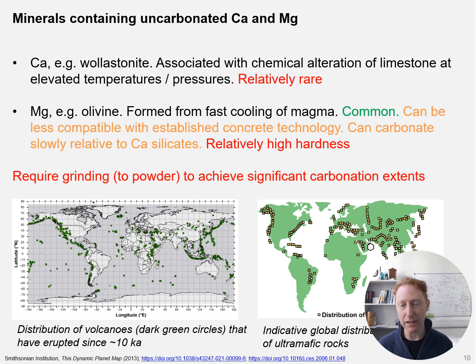So the good thing about magnesium silicate minerals is that they are relatively common. Wollastonite, on the other hand, is much rarer, and so in general has a more limited potential as a feedstock for CO₂ mineralization. Regarding the more available magnesium silicate rocks, magnesium is less compatible with established concrete technology. For example, Portland cement requires limited magnesium content, so it can be used in limited, but still quite a few, applications. Another issue is that magnesium silicate minerals have relatively high hardness, and this is a problem because they need to be ground into a powder or a small particle size to carbonate them significantly, and this means higher energy, or in this case, electricity demand.